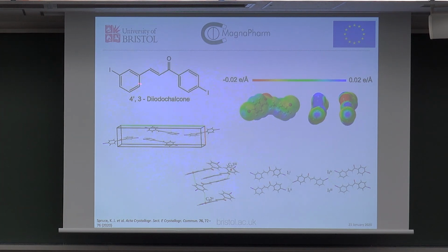So a quick example. This is just a little paper we've just published about a diiodochalcone. This motif in the middle is a chalcone, and we've got two iodines on each end. Up in the top right, this is a calculated electrostatic potential of that molecule. So effectively, we're looking at how electropositive or electronegative that molecule is at certain regions. And we can see here, sort of around the oxygen, we've got a red zone here, which means we've got a slightly electronegative region, as would be expected of oxygen. And then, because of that, we then have this electropositive region in the backside, because it's pulled that electron density over to the oxygen.